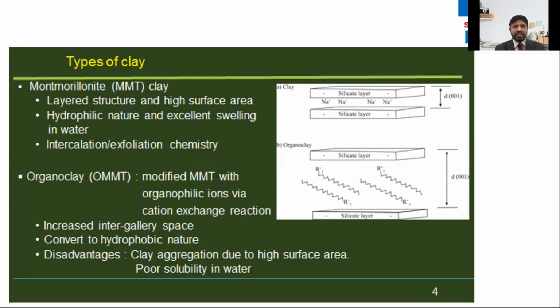Type of clay. You can see the structure of clay. It has a layered structure. That's why it is called layered silicate. In the layered silicate, clay layers are connected to each other by an interlayer space. Most of the clay layers carry a negative charge, and simple cations in the interlayer space hold the clay layers together by electrostatic attraction. By applying mechanical forces, such clay layers can be separated. Separation of clay layers is very important if you need to prepare nano-composites. It is the most important step. Normally, we neglect it in our research. There are so many types and grades of clay, but in my research, I selected montmorillonite clay because it has a higher interlayer space and swelling behavior.